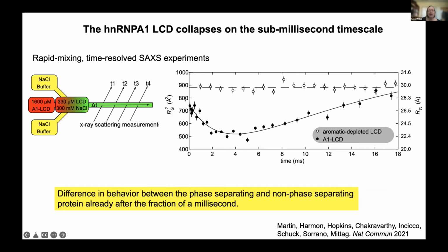And what he observed was that the protein first compacted, and that reflected that in the salty solution, the protein became less soluble, and now we could see the effect of the aromatic interactions, of the sticker-sticker interactions, and then it started to assemble. While this mutant, which was missing two thirds of the aromatic residues, didn't really show any change. And so there's already a difference in the behavior after a fraction of a millisecond in this protein.